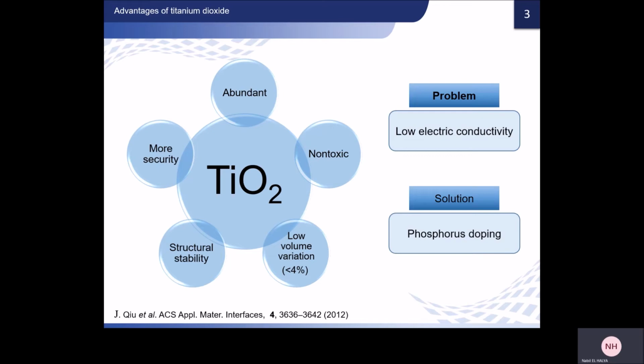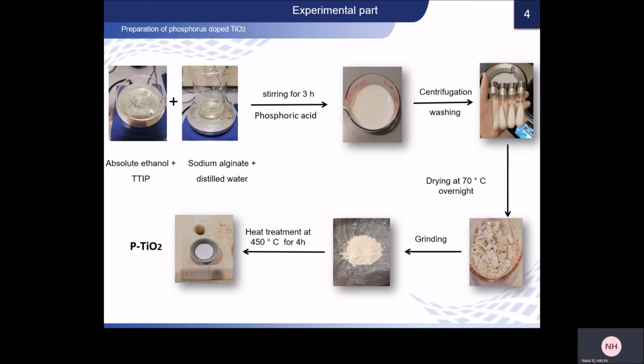In this work, we are interested in phosphorus doping using phosphoric acid as phosphorus precursor. So concerning the experimental part, the P-doped titanium dioxide nanoparticles were synthesized via sol-gel method. Typically, titanium tetra-isopropoxide was used as titanium precursor, then sodium alginate biopolymer as complexing agent were used in the form of solution, and phosphoric acid was used as phosphorus precursor.